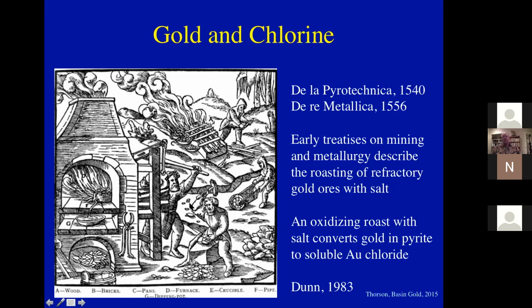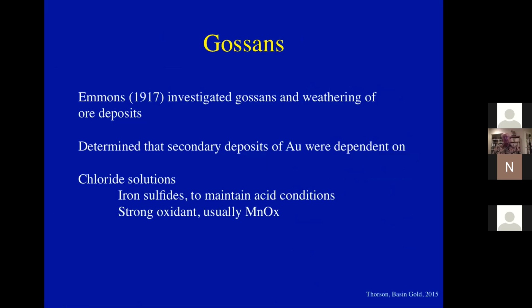And when you roast gold ores with salt, the oxidizing roast with the salt converts the gold in pyrite and other insoluble gold minerals to a soluble gold chloride that can then be leached out of the rocks. Now, Emmons did some work on gossans in the early 1900s, investigating the weathering of ore deposits, and he determined that secondary deposits of gold were dependent on chloride solutions, iron sulfides, which maintained acidic conditions, and required a strong oxidant, usually manganese oxide.